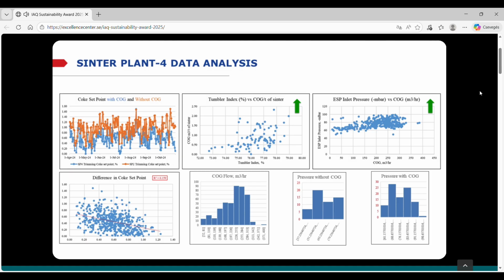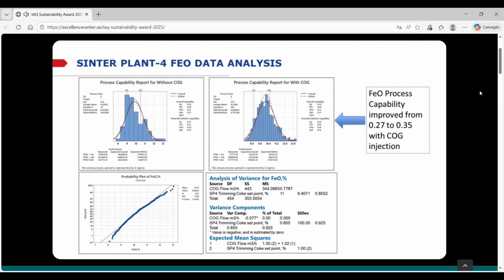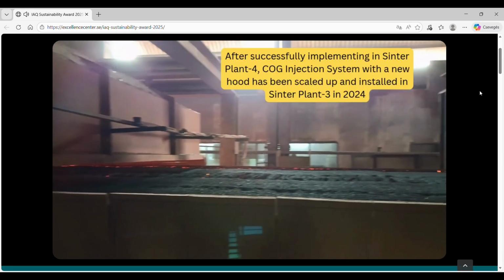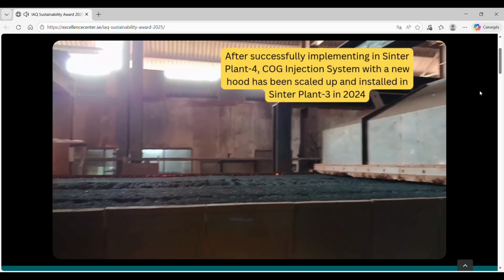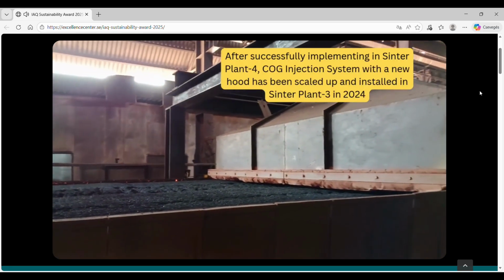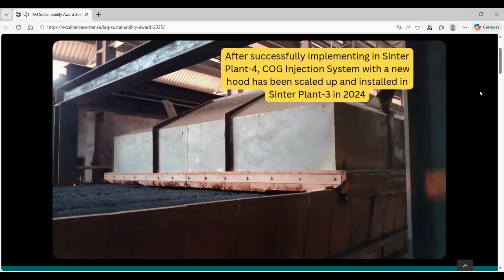Sinter plant 2 and 4 consume the base mix from a single source. With COG being injected, sinter plant 4 consumed less coke, as seen by the coke run chart. The tumbler index and suction increased due to COG. Analysis of variance shows the process capability of FeO increased from 0.27 to 0.35. After successfully proving the industrial scale concept, the COG injection system was installed in sinter plant 3, which is double the capacity of sinter plant 4.